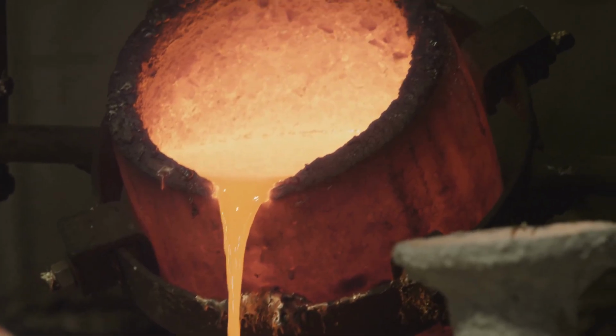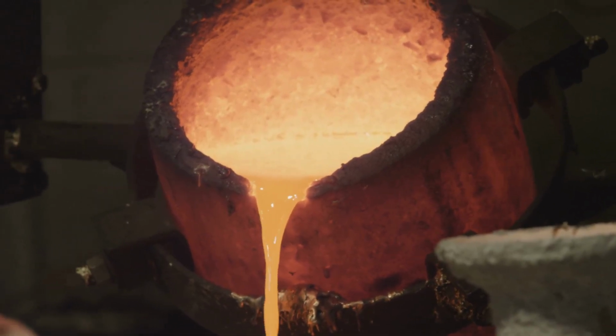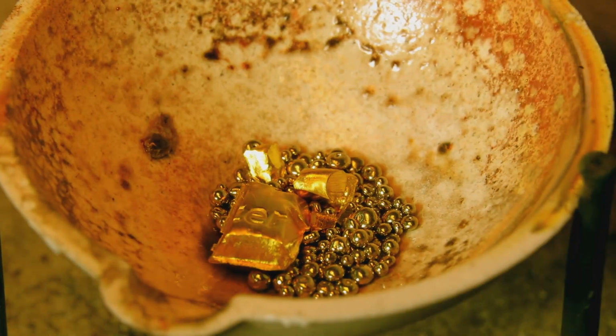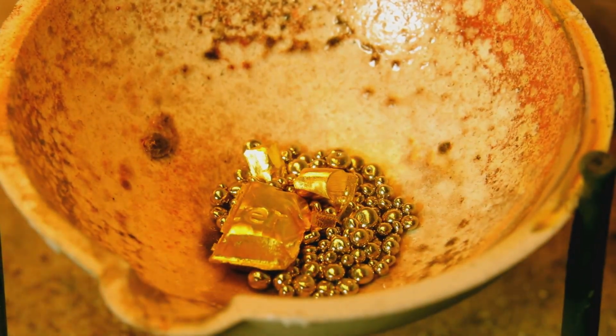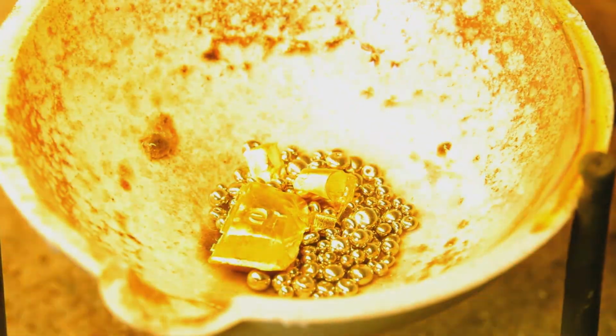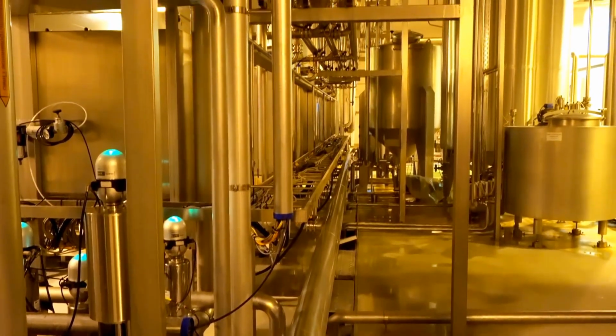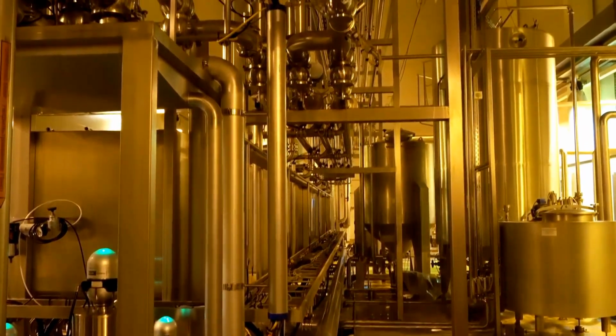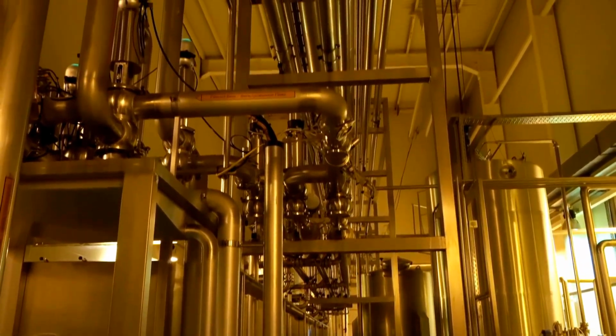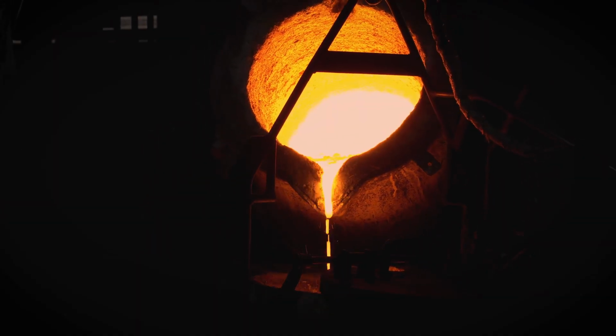Next, electrowinning, smelting, and the dramatic pour. In electrowinning cells, anodes and steel wool cathodes attract gold ions under electric current. Gold deposits as a sludgy solid, then is washed, filtered, and dried. Still a mixed concentrate. The recipe has to be just right.